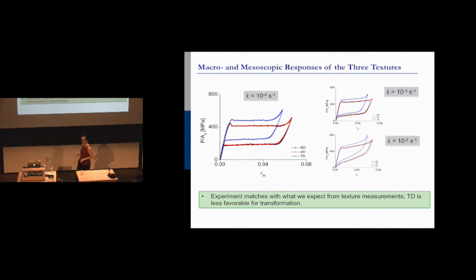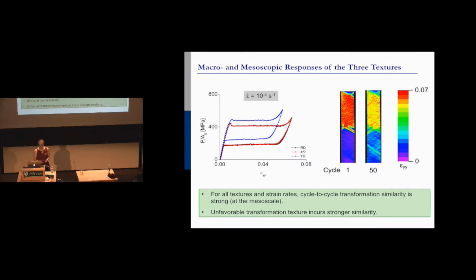But what does that mean for the similarity? Well, it turns out that if you have an unfavorable transformation texture, if you cut your stent perpendicular to the rolling direction of the sheet, you will get less squishiness, you'll get less superelasticity, but you'll have more predictability. You'll have more transformation similarity from cycle to cycle. So it's kind of a trade-off. You can get a stent that performs not as well, but you can predict it better.